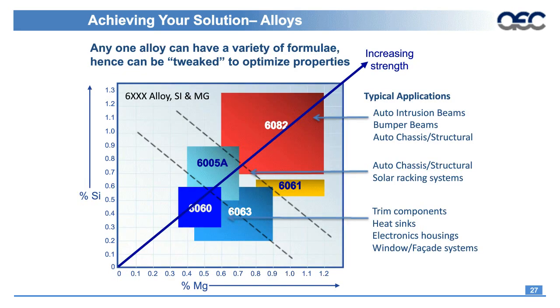So within the 6000 series, silicon and magnesium are the primary alloying elements. You can see the difference in the amount of the alloying elements that are put in, and then how that translates to increased strength. So normally in a B and C application, towards the bottom there is 6063. A lot of times that's a good alloy for non-structural components, heat sinks, electrical housing, windows, doors, that type of thing. And we start moving up into the higher strength, the 6082.